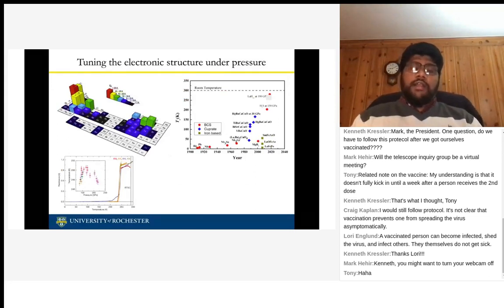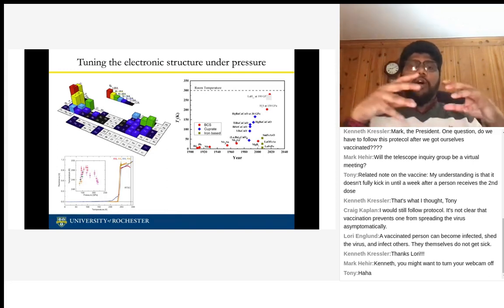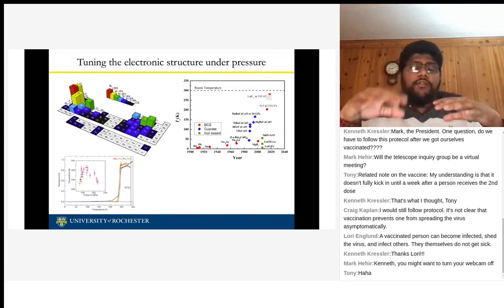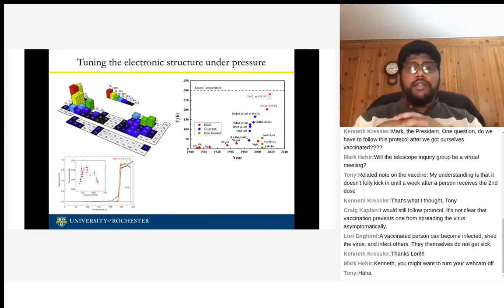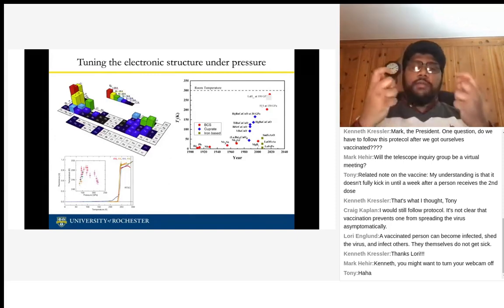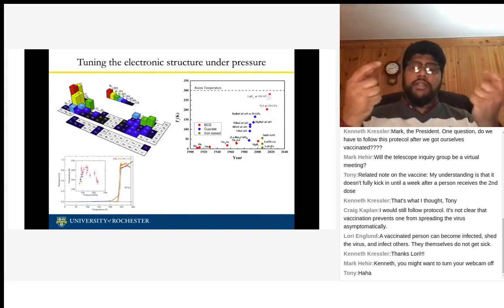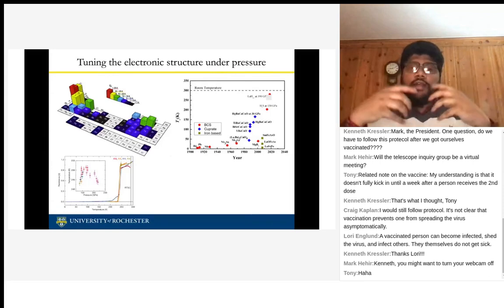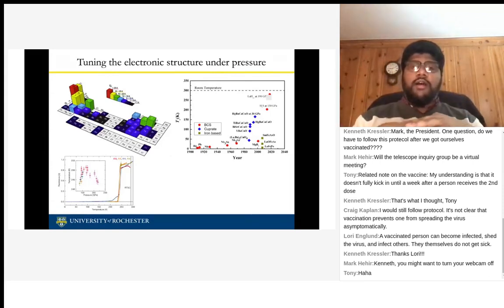and the superconductor, in general, not all the materials in the periodic table are superconducting, and any compound that we put together may not be superconducting. But with pressure, we can obtain optimum conditions that can favor these superconducting transitions. So people started to use pressure as a tuning parameter instead of doping, as a way to get the right conditions for a material to have a superconducting transition.